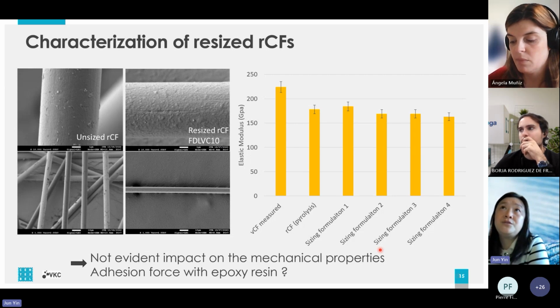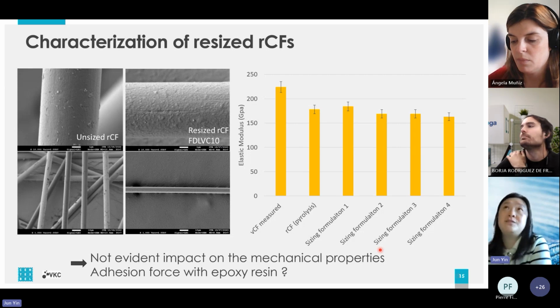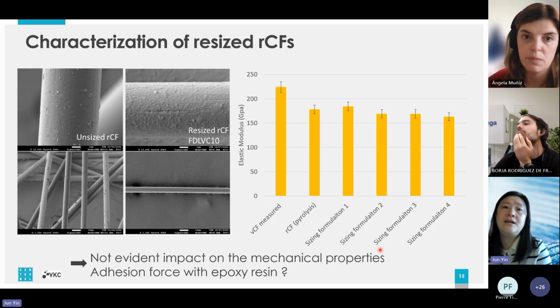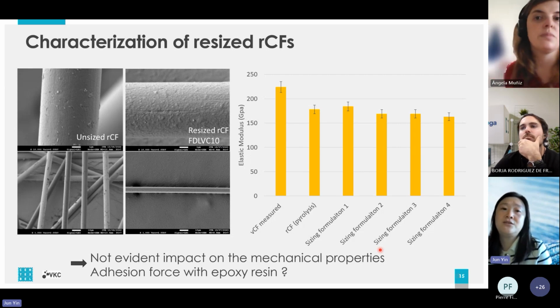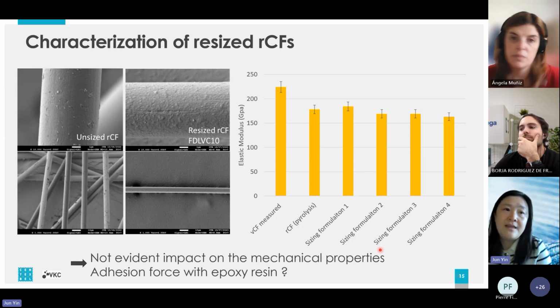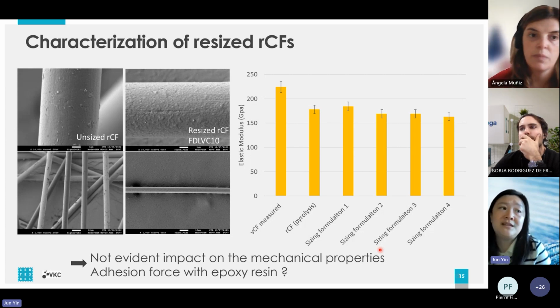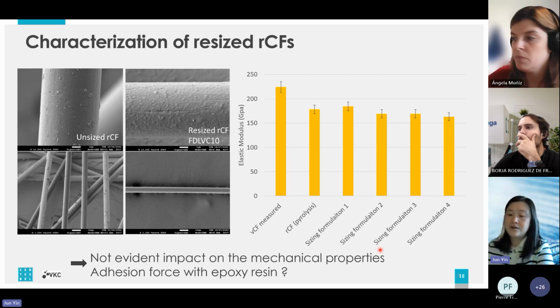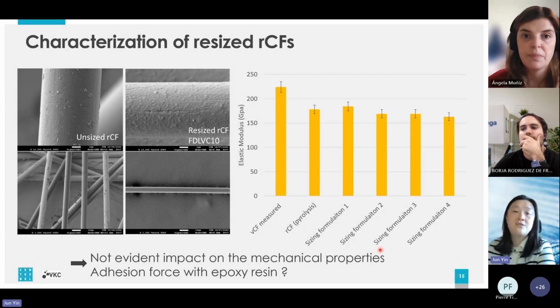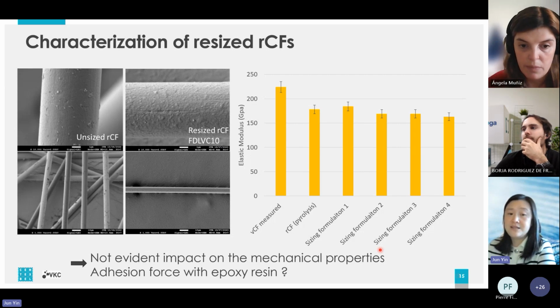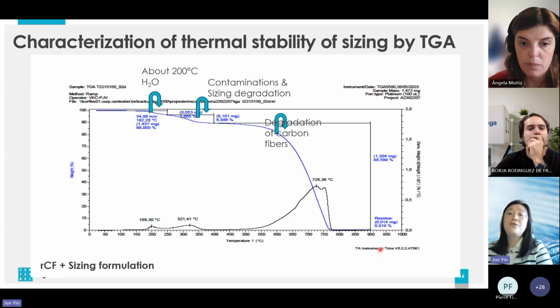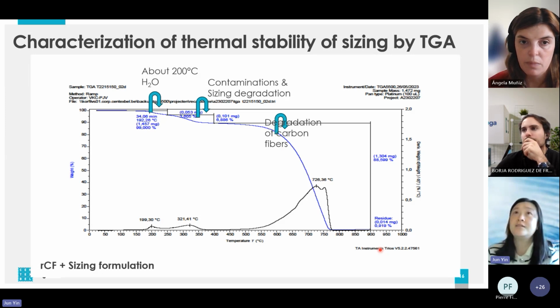That means we put one single fiber in a drop of resin, then pull it out of the resin. But for the moment, we don't have this method. So we try the second possibility: we reuse all these fibers to produce the composite. Then we do the mechanical property test on this composite to get to know the adhesion force of these fibers with epoxy resin. But before using these fibers in the composite, we want to check the thermal stability of